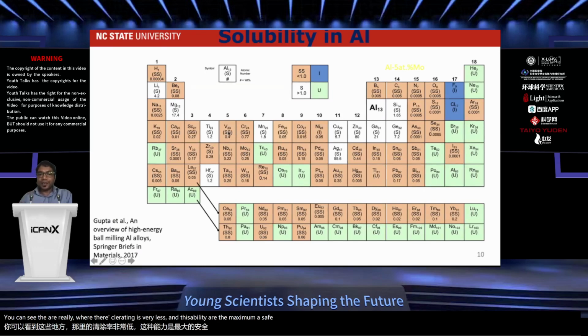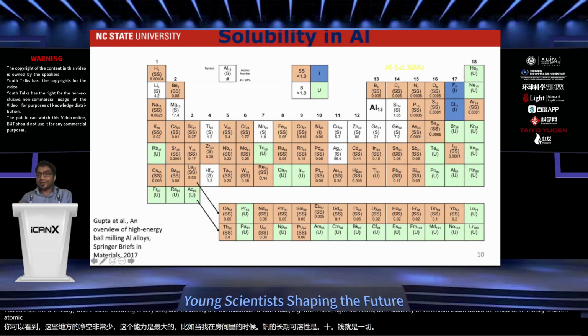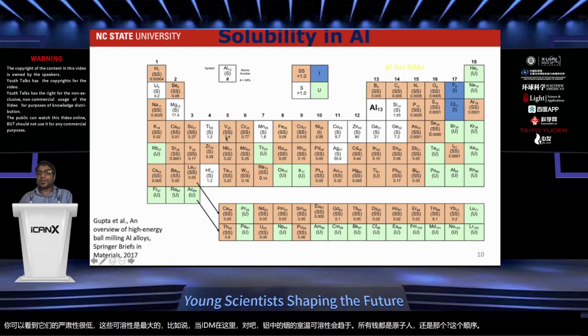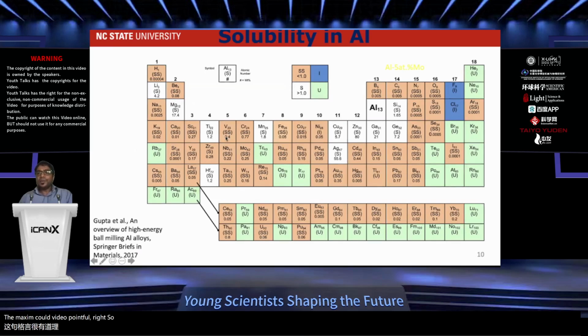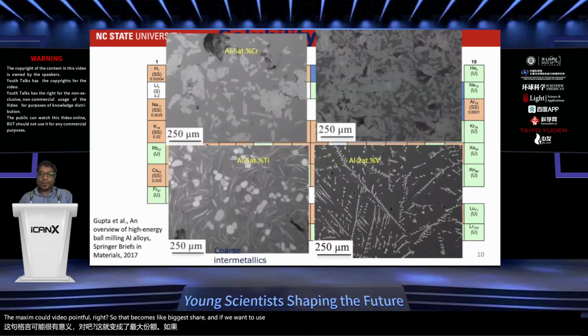Say I take vanadium, for example. The room temperature solubility of vanadium in aluminum would be 10 to the power minus 7 atomic percent, that order. The maximum could be 0.4. So that becomes the biggest challenge if we want to use them.